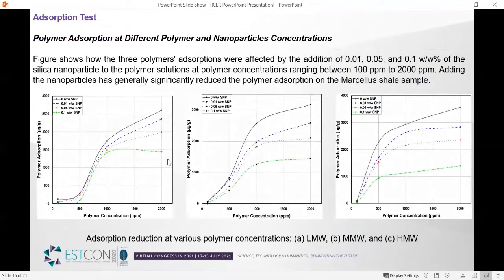So polymer adsorption at different polymer and nanoparticle concentrations. From the figure, we can see that the three polymers' adsorption were affected by the addition of different concentrations of the nanoparticle at polymer concentration ranging from 100 to 2000 ppm, and adding the nanoparticle, as can be seen, has generally significantly reduced the polymer adsorption on the Marcellus shale sample.